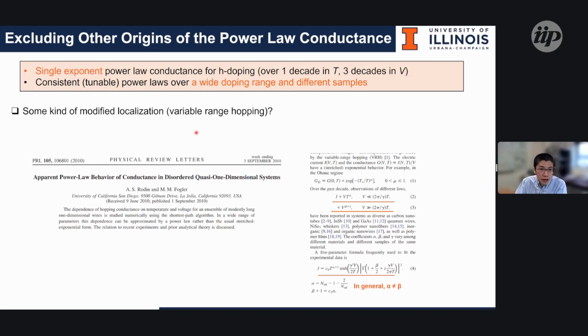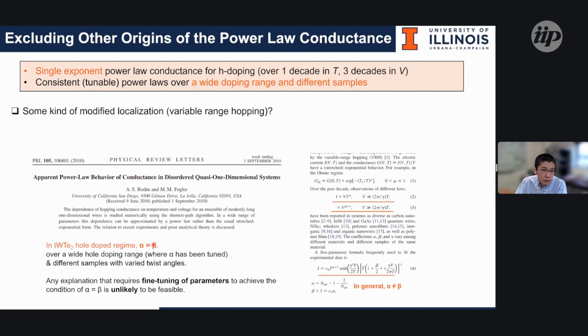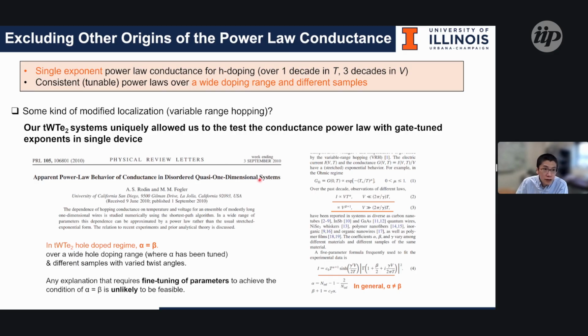There were also other proposals arguing that in such a quasi-1D structure, if you have some amount of disorder, it could also create the so-called apparent power law behavior. But those people were proposing that the power law scaling parameter for the temperature and the external bias should be different. In our case, we are seeing that the power law is equal for the external bias as well as the external temperature. So in our system, it's very unlikely coming from disorder.